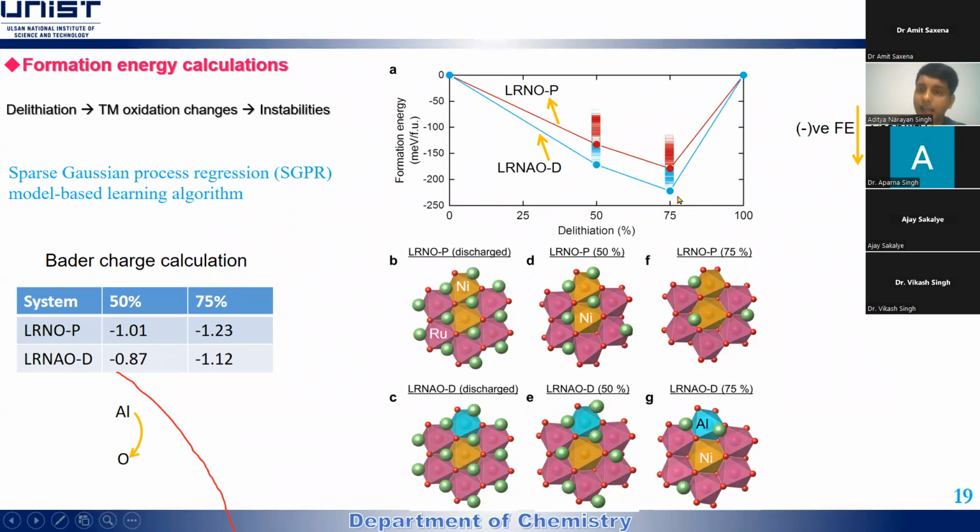But after a certain extent, it starts exploding. In reality, only lithium extraction of 60 to 70% is allowed, but we extracted lithium to 75%. When you remove all of your lithium, as a material scientist, there will be lithium vacancies. And when lithium vacancies increase to a certain extent, the crystal will collapse. And it happens in reality. What we could see is that though our material sustained 75% extracted lithium, after further removing the lithium, it will distort or collapse the crystal structure.